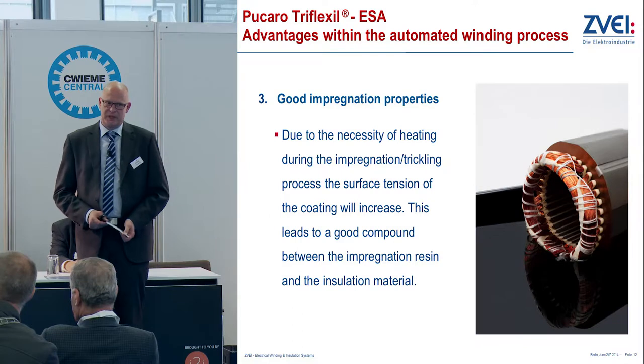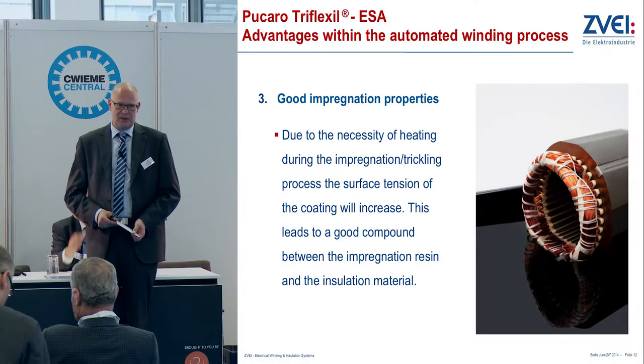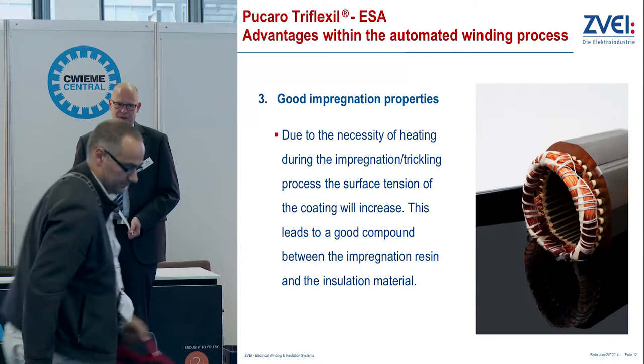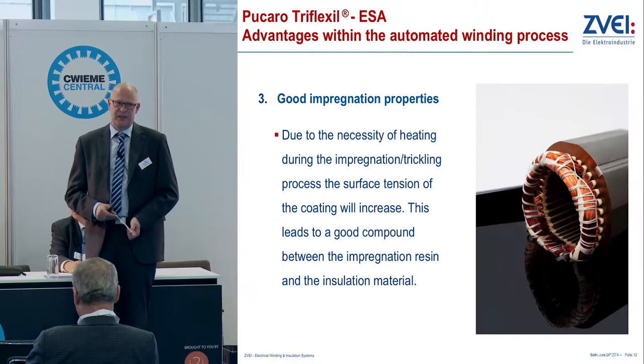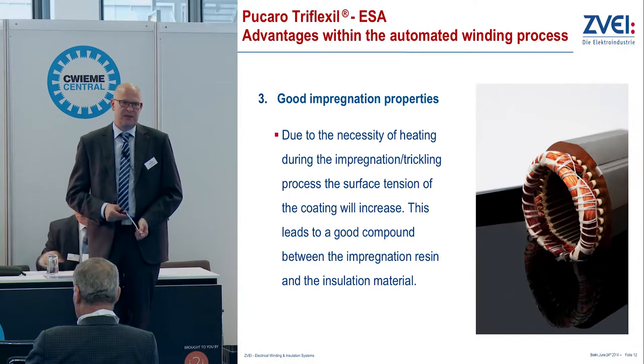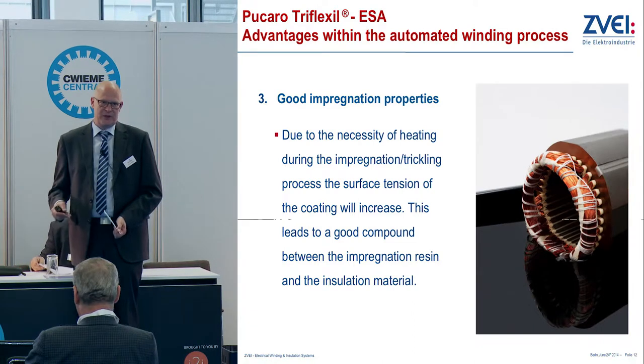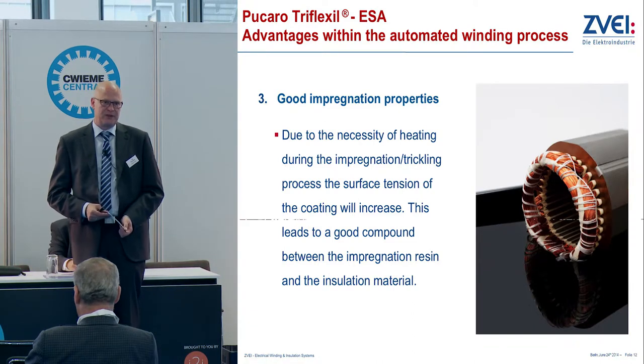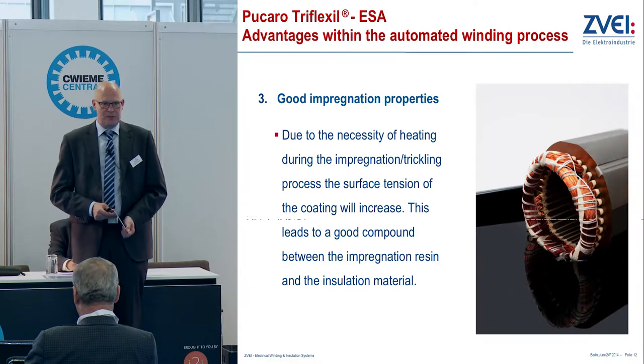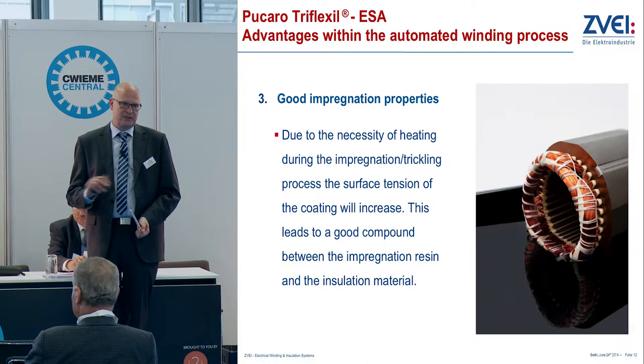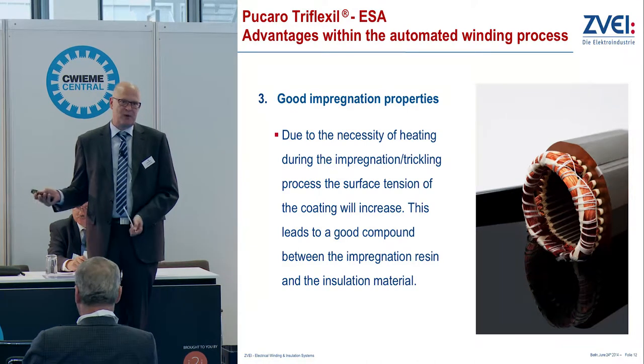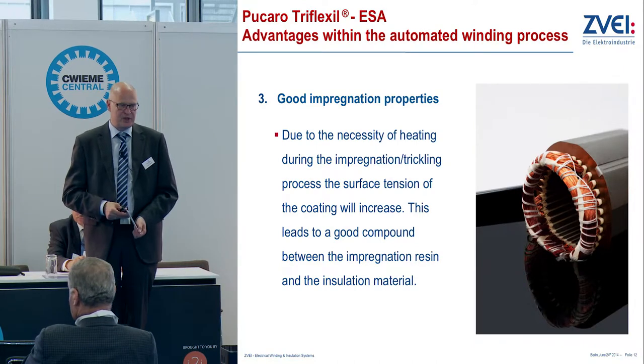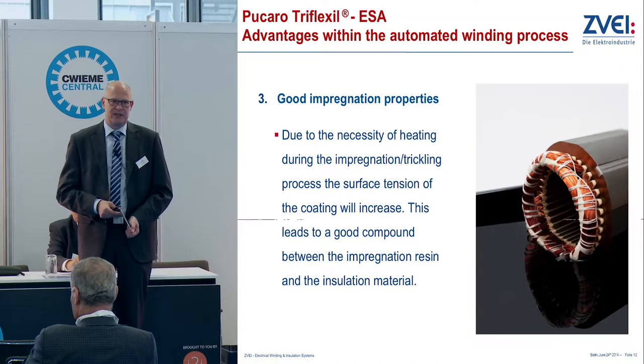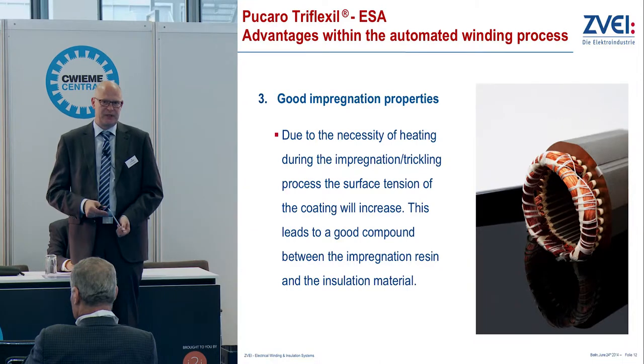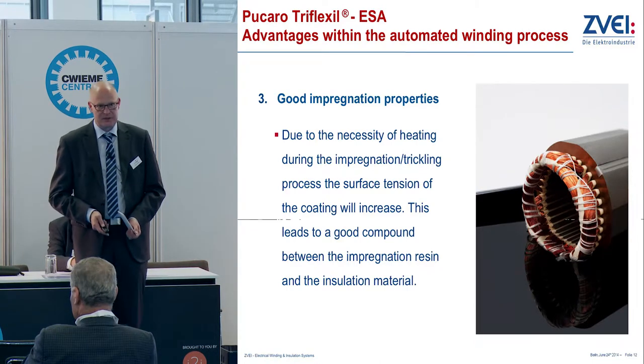There are already materials in the market which are also supposed to have an extra slippery surface, but these materials use an additive based on fluorine, and this additive will always prevent the trickling resin from adhering to the insulating material. In our case, our additive will migrate back into the coating layer by heating up over 60 degrees, which is the common use temperature during trickling. So the trickling resin can easily adhere to our material and you get a really compact winding afterwards.